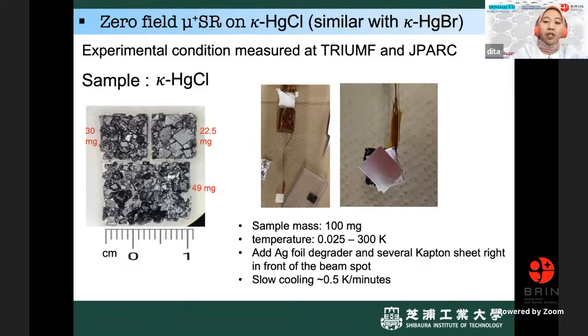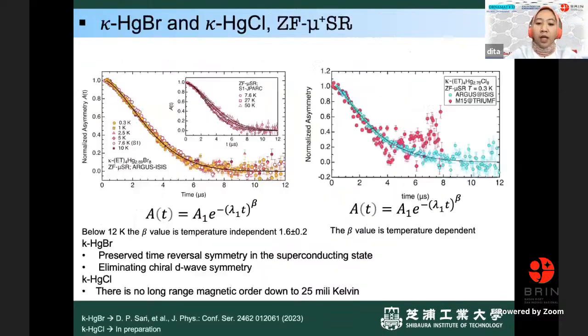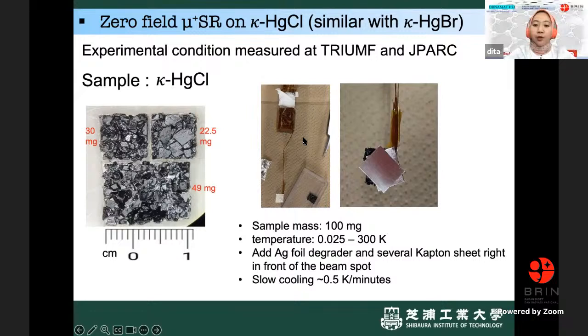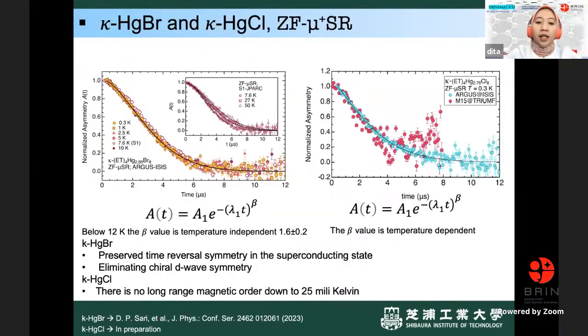Okay, then we measure μSR to see more detail. So this is the crystal, and we need much more mass of the sample for μSR measurement, in total about 100 milligram. For the SQUID, we only need like 7 milligram. So imagine that I put my sample here in the spectrometer that I showed in the schematic figure, and then this is the spectra.